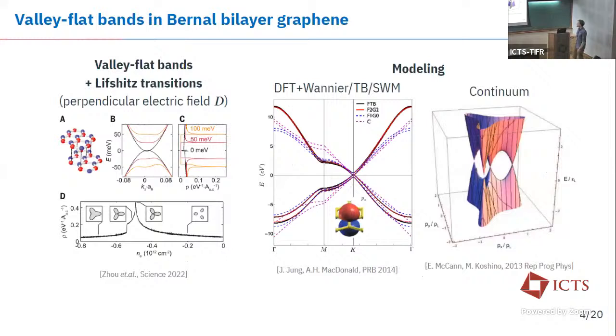Now, all of this is very nice, but from a theory perspective, it is very hard to model those materials. And that is because we have flat bands, flat sections of bands, only in a very tiny part of the Brillouin zone. Here again, you see a picture of the band structure of Bernal bilayer graphene under a vertical electric field. And you see how the bands flatten in a tiny region around the K points, and you have van Hove singularities in both the conduction and the valence band that kind of drift apart when you set the electric field larger.